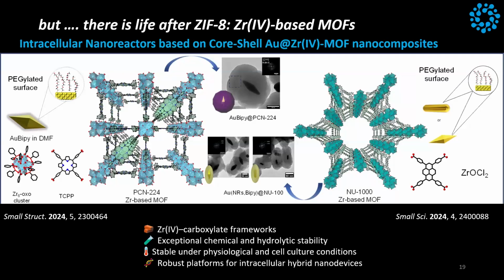What we found, as I already mentioned, is that if you increase the temperature, which is normally what you need for making this zirconium-based MOF, you change the morphology of the particles. And then they are not interesting for me. If I have a rod or a bipyramid or something that has very cool properties in the near infrared that I need for excitation, if I end up with a sphere that has the absorption in the green, it's not useful for me, okay?